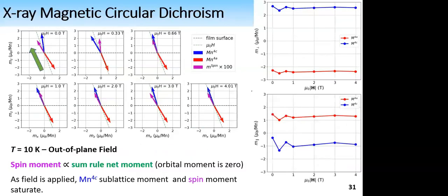Now we want to see what these diagrams look like. I'm showing you a very basic example. This is data taken at 10 Kelvin with the field applied out of plane along the green broken line, and the field was directed as the arrow is pointing. There are 3 different arrows I'm showing in these diagrams. First is the blue one corresponding to the 4C moment. This one is dominant because we are below compensation. Then we have the red arrow, which corresponds to the 4A moment. And there's the pink arrow, which I had to multiply by a factor of 100. This corresponds to the spin moment, which is proportional to the sum rule net moment.